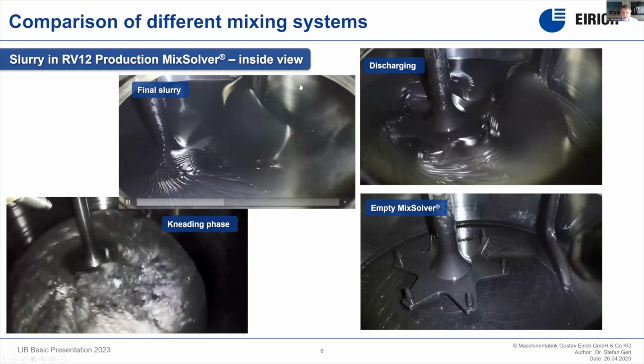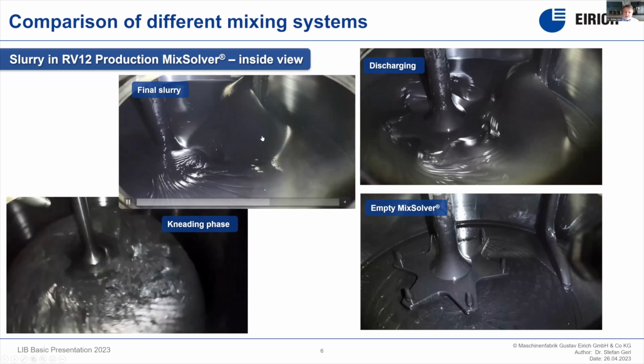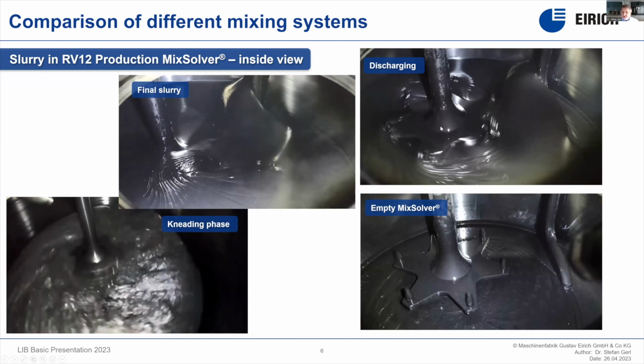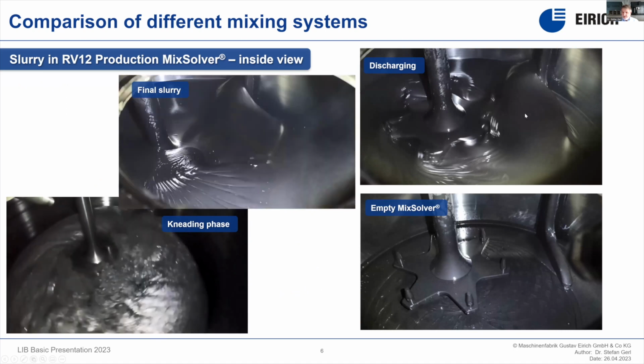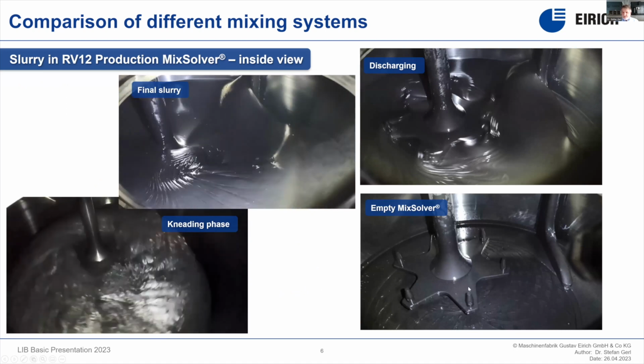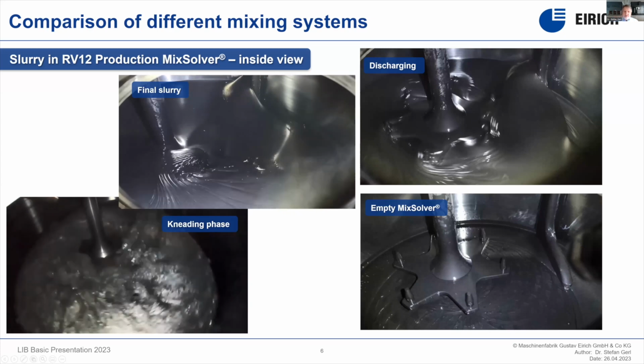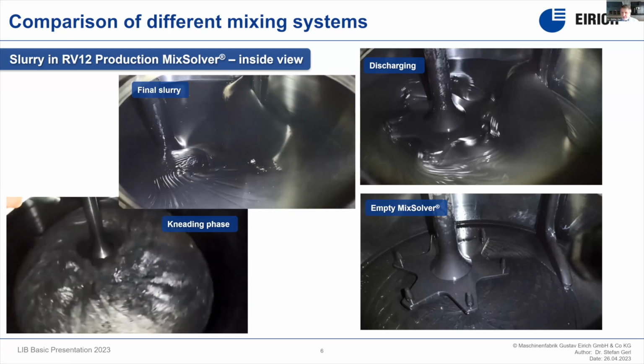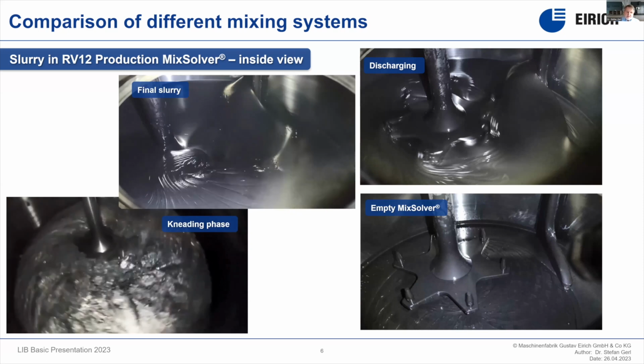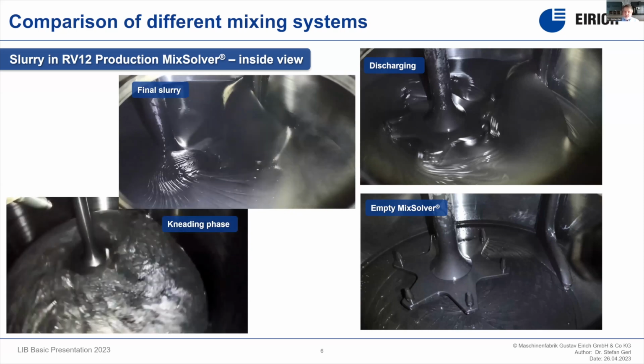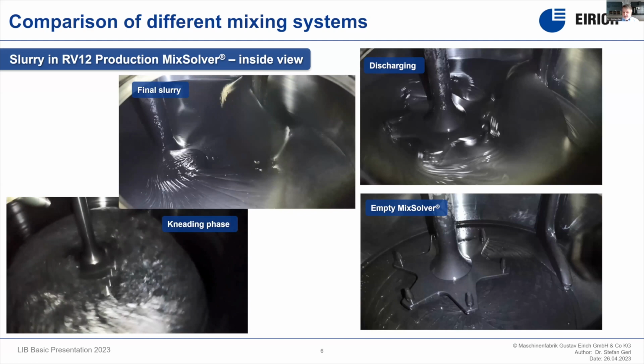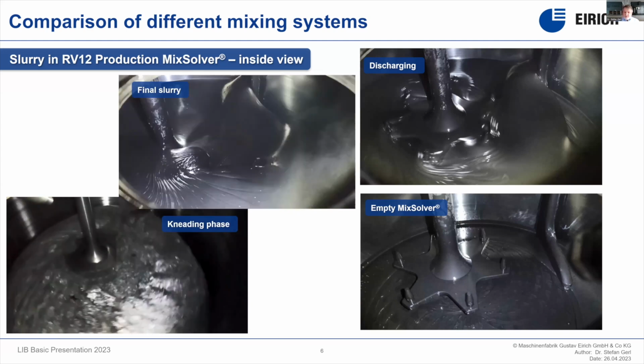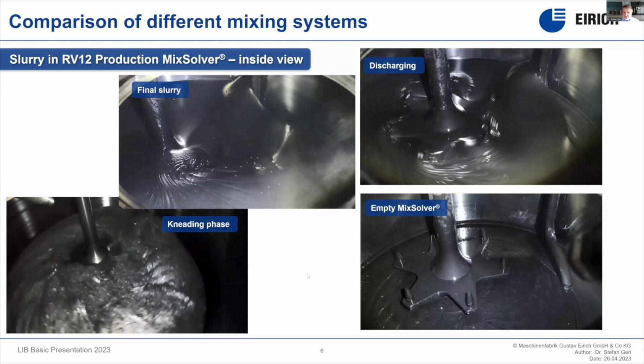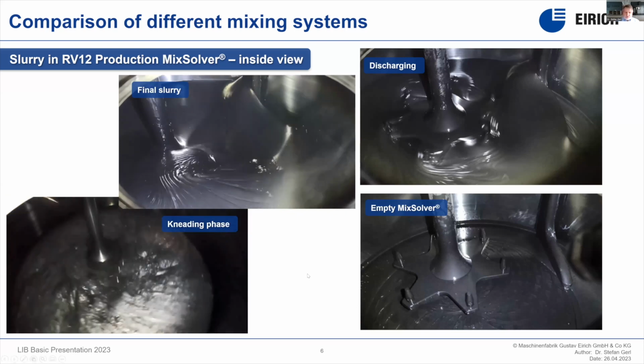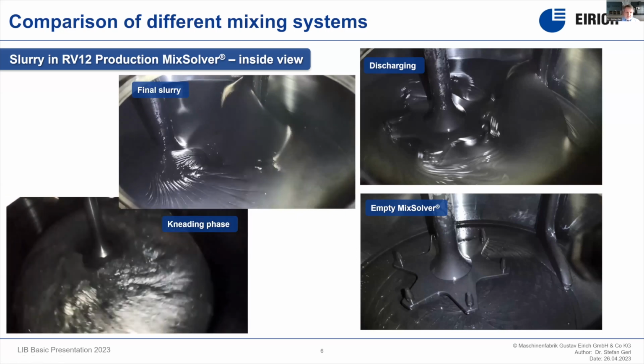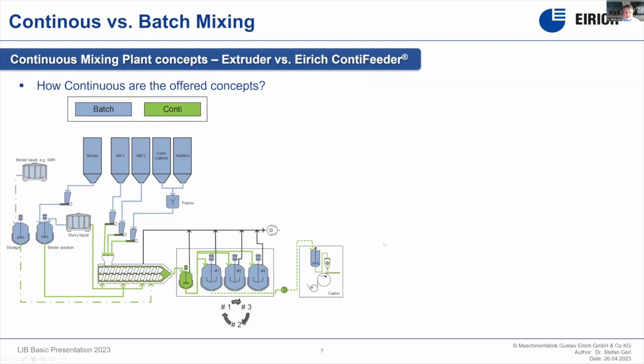You see the clean walls, which come from the effective wall scrapers. And here during discharging of the slurry, at the end, we have a very thin layer of liquid covering, for example, the mixing tools, but this doesn't interrupt our process. So if we are working in a gigafactory batch by batch, this is good enough to prevent any problems in repeatability. And by this, we can make sure that we have a high output out of a very small machine.